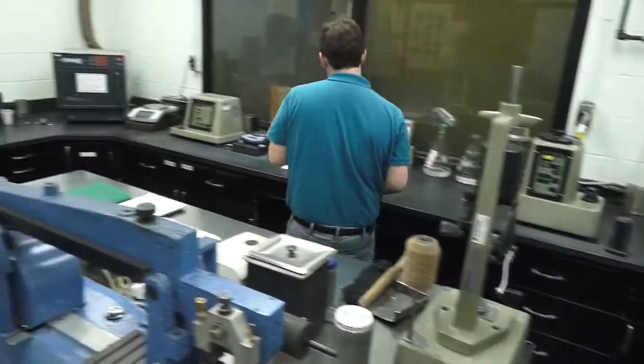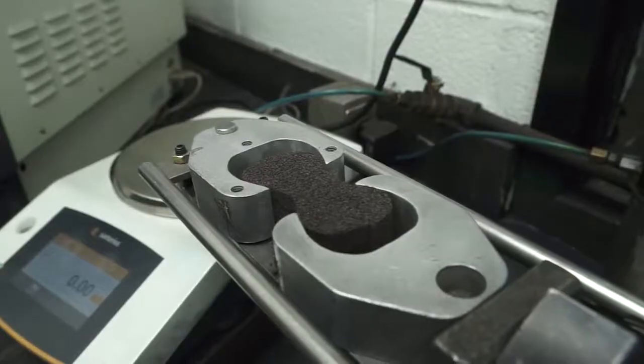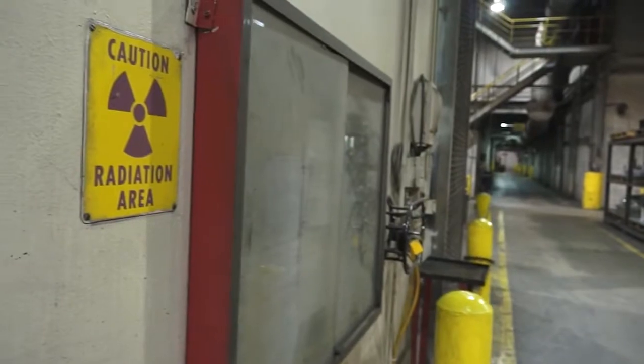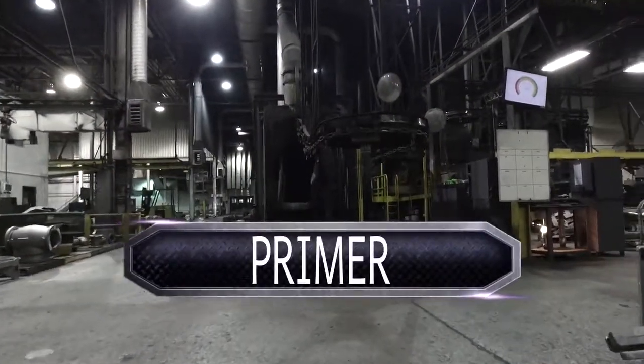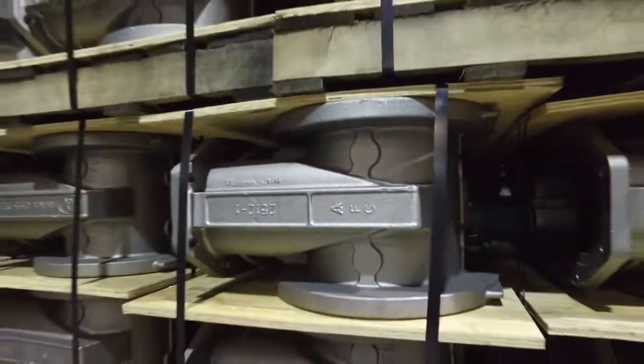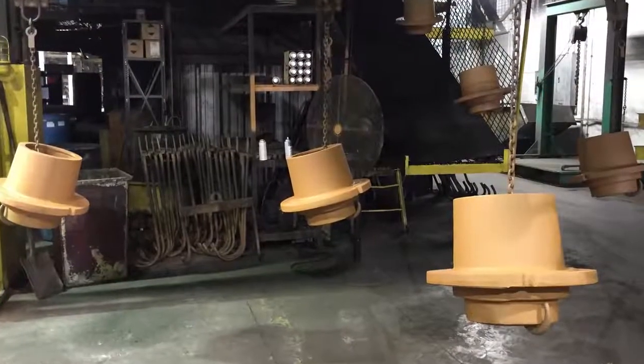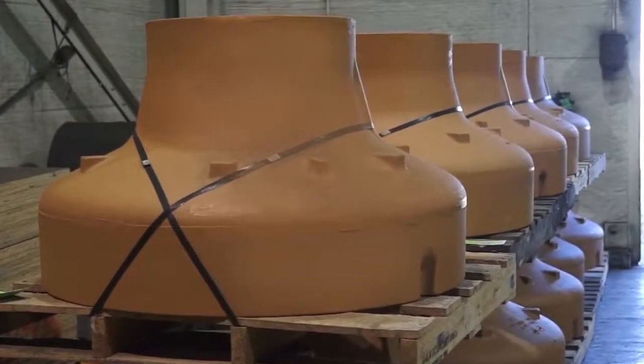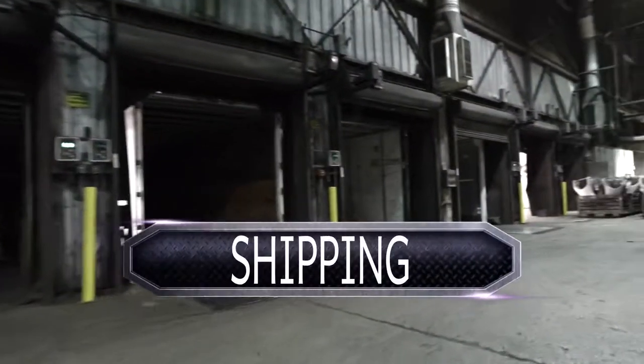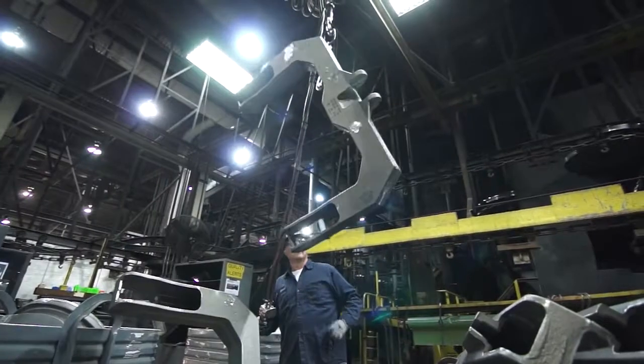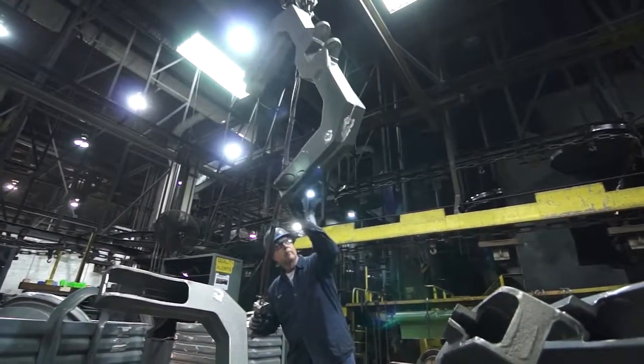In the sand lab, the sand is evaluated to ensure it meets specifications. Non-destructive tests include ultrasonic testing for flaw detection, nodularity, and thickness. American Castings also has X-ray capabilities and certified inspectors on site. Depending on customer specification, American Castings can apply a primer, either in-house or through local paint shops. Finally, one last visual inspection completes the casting process. The casting is ready to be shipped to the customer.